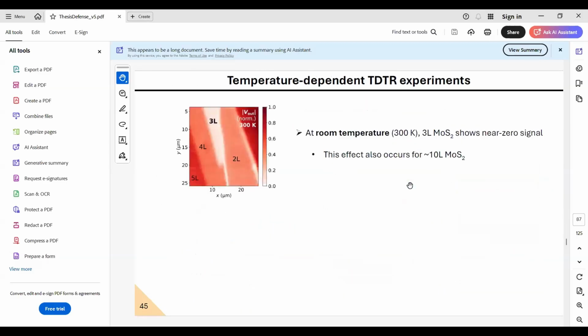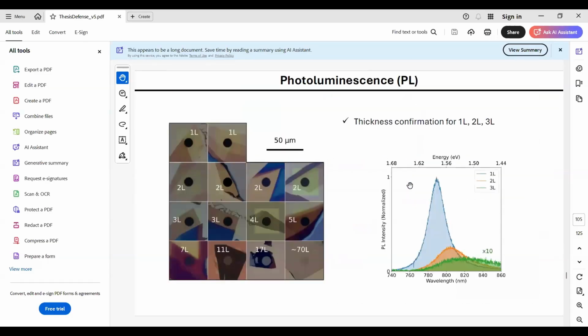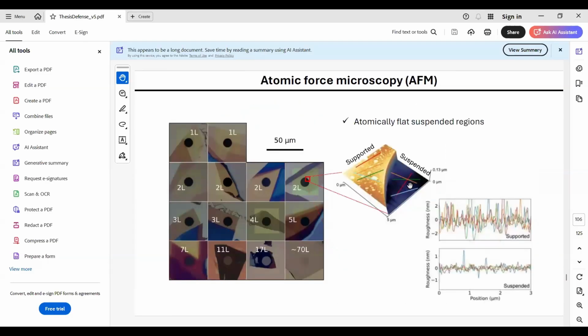Yes, thanks for this question, because I didn't have time to show it. So yes, indeed, we performed AFM both in supported and suspended regions, and we observe sub-nanometer roughness in the suspended regions and 1 to 2 nanometer roughness for the supported regions. Okay, very nice. Supported on gold, so it forms these blisters, which we avoid in our measurements, but still it conforms very well with the roughness on the supported part.